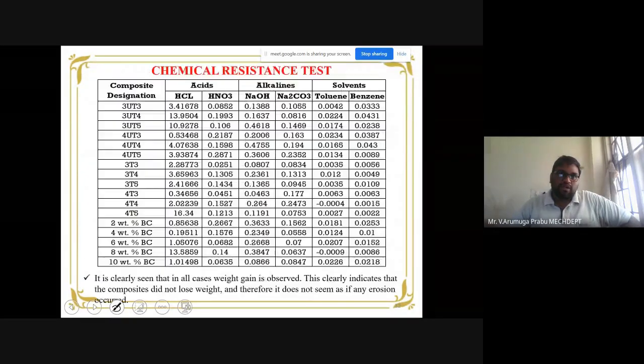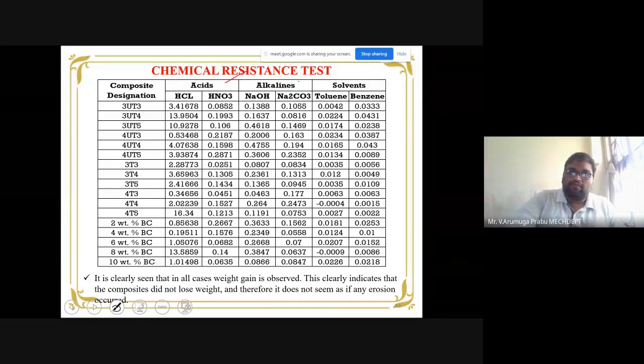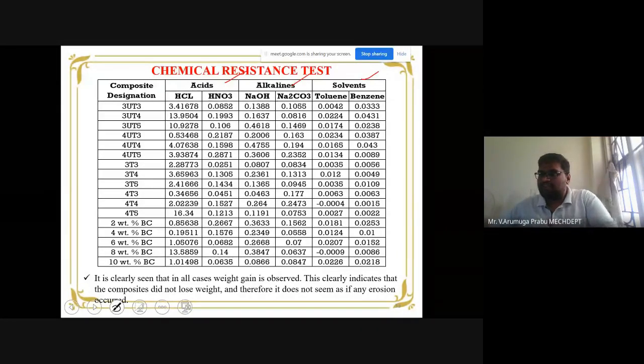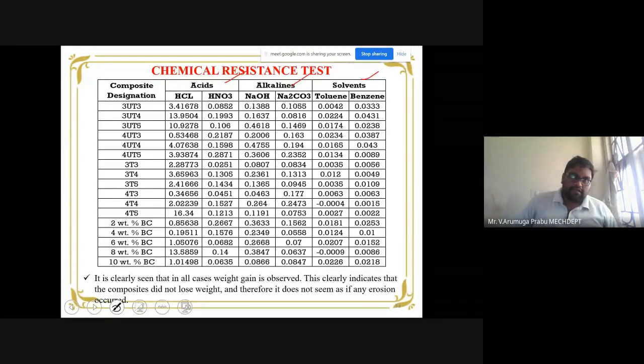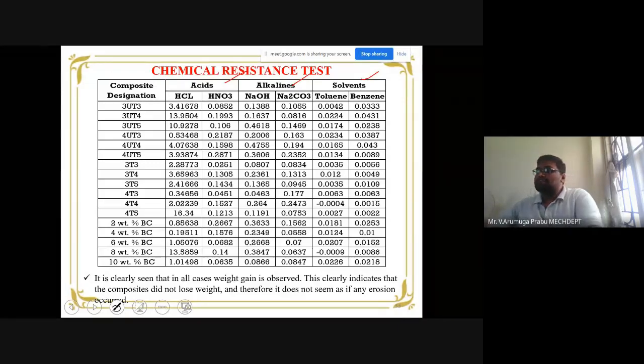Then the last test that I would like to discuss with you for another 2-3 minutes is the chemical resistance test. So we subject the prepared biochar-based natural fiber composites to acids, alkalines, and solvents, two of each. Two acids are taken, as noted in the table, that is HCl, hydrochloric acid, and HNO3, nitric acid. Then alkalines are taken, sodium hydroxide and Na2CO3, followed by the two solvents, toluene and benzene. Okay, so these are all the various acids, alkalines, and solvents we have chosen to carry out the chemical resistance test.